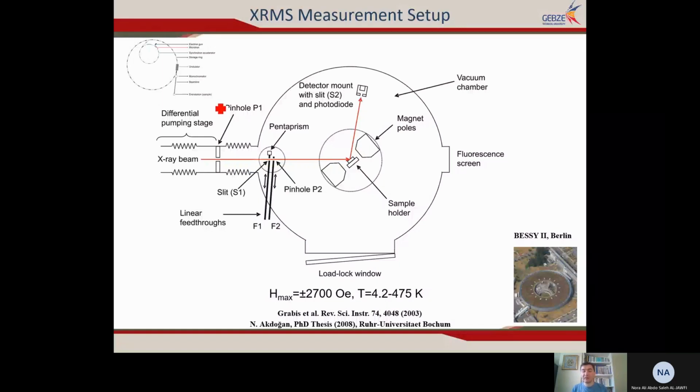I will go into detail, but here let me tell you that we need to change the polarization and the energy of the incoming photons. For this reason, you need synchrotron radiation. In addition, high intensity is very useful in these experiments, so synchrotron radiation is obligatory. You cannot carry out this experiment in the lab.